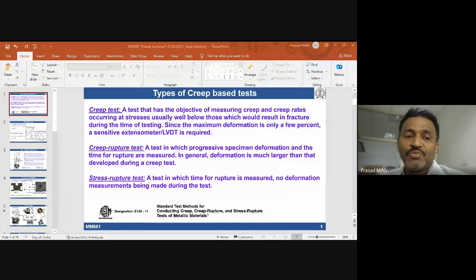Okay, so one can use a Larson Miller parameter, which basically takes into account the combination of temperature and time to rupture. From that I can determine the stress requirement for a given Larson Miller parameter. What is the stress below which the material will be safe, above which the material will be unsafe, at elevated temperatures? So we had this discussion. It basically comes under the category of creep rupture.